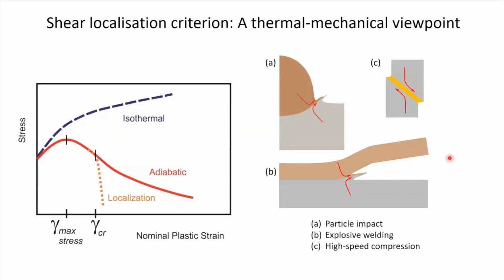And later on, we realized that this localized deformation is a very well-known phenomenon, but not in bonding, rather in fracture. For materials that have this capability to show localized deformation, normally this leads to instability in the deformation and you get rupture. But in this case, we thought that it could be one of the factors playing a role in bonding. This is generally called shear instability. But as I said, shear instability normally is something that you get during tension and it leads to rupture.